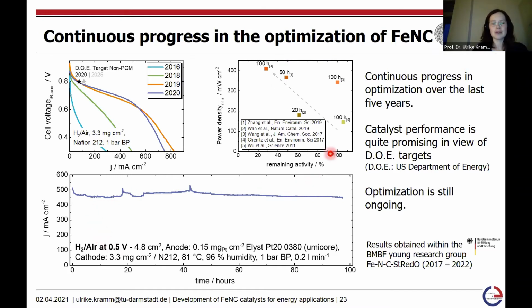And what is typically observed for this group of catalysts is this type of trend. Either you have a good activity but a very poor stability, or you have a good stability but typically you do not reach high current densities or high power densities. This is somehow really a kind of exception. So our point is more or less here in the middle, but we still already obtain some more results. So it looks like we can at least push a little bit more in this direction.